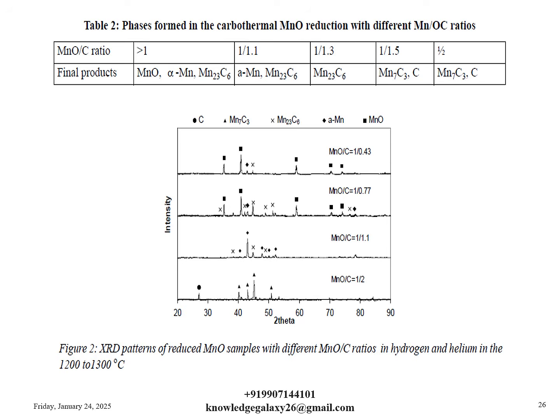And this is the graph, figure 2, XRD patterns of reduced MnO samples with different MnO by C ratios in hydrogen and helium in the 1200 to 1300 degrees Celsius. Okay, moving ahead.